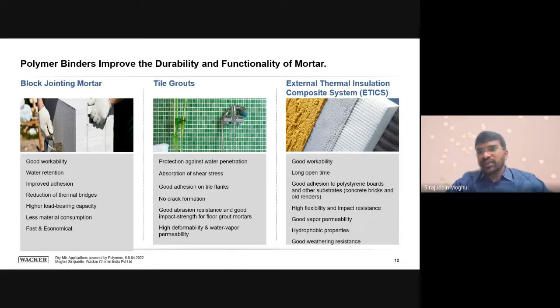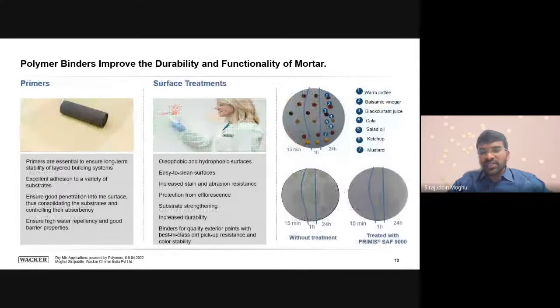You cannot adhere, for example, even thermocol, which we use as an insulation material. You can adhere thermocol with a polymer modified mortar. That is how it is going to enhance the tensile adhesion of the mortar. And we can also use it for primers. Primers, like I was mentioning, are for when multiple layers come one onto the other. We need to make sure these layers are bonding very properly so that there is no unsoundness between them. In such cases, we use primers.